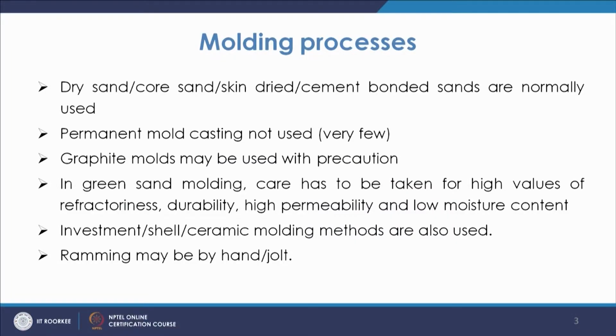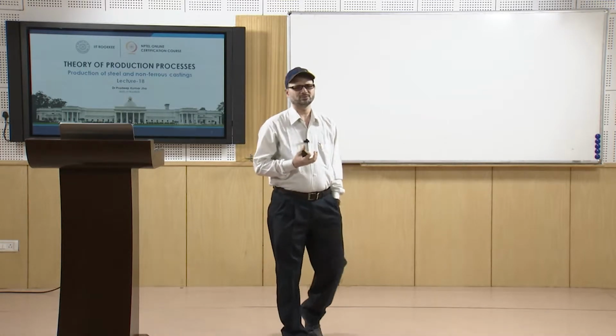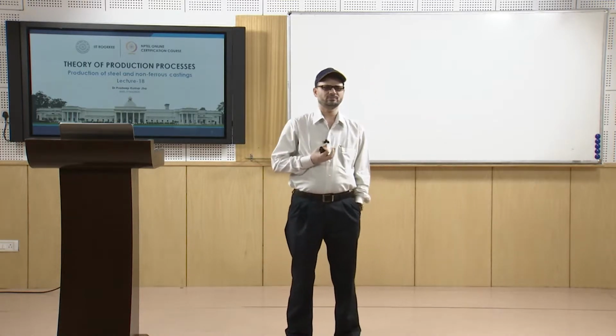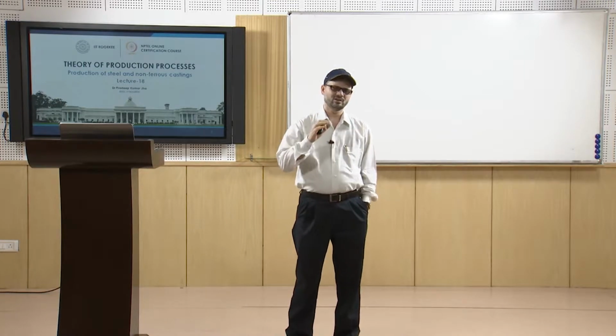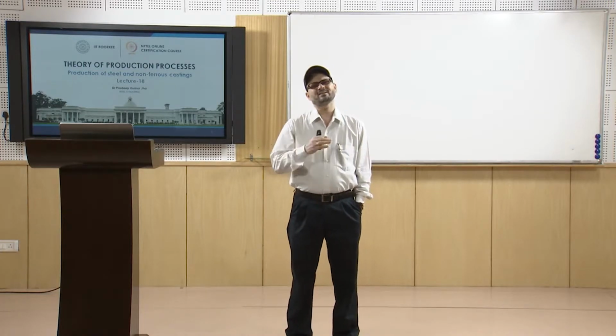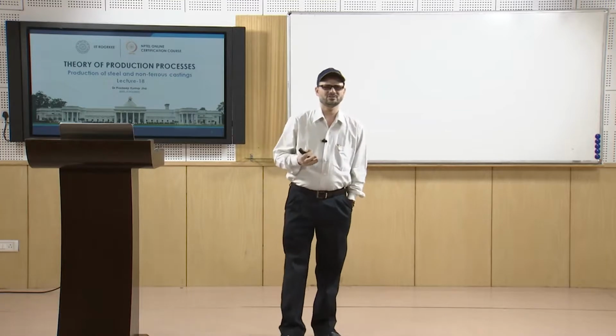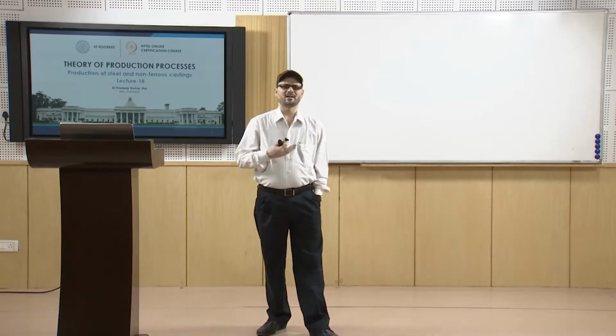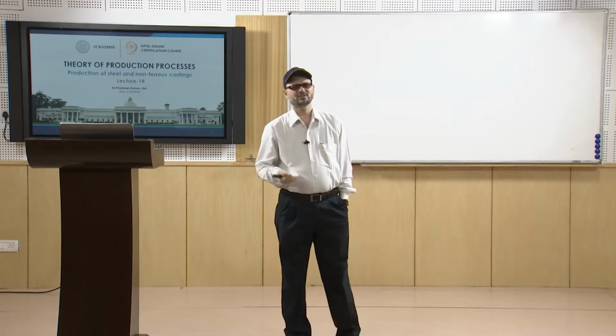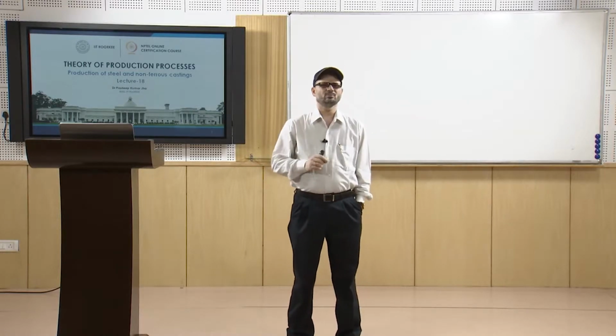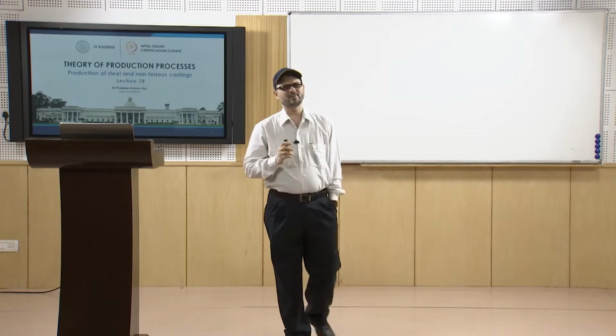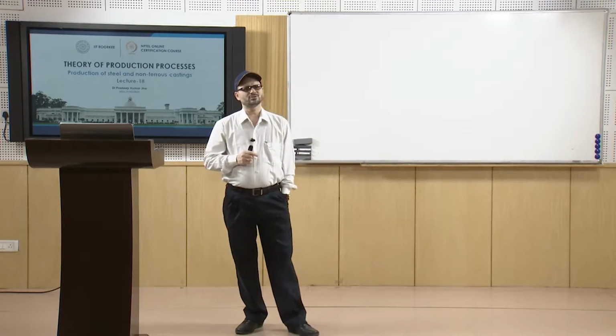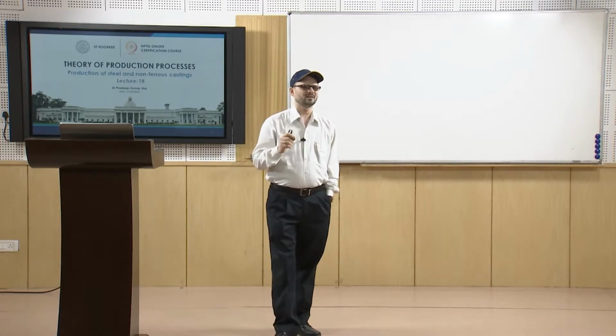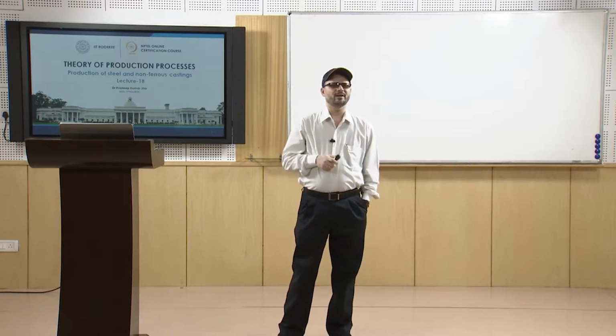So that is a special challenge in case of steel casting, because the proper control of carbon is very much important. If you do not have the adequate or the optimum amount of carbon, it may lead to formation of carbides. It may be iron carbide, it may be carbide of alloying elements. So carbon percentage is very much an important factor, and graphite molds are used only with precaution that the carbon pickup should not be there.